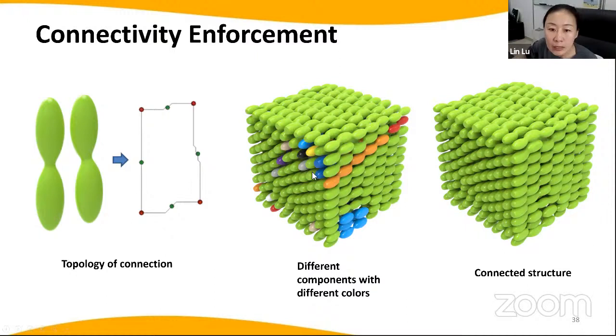For example, here this is the pore structure. The colored pores, rather than the green pores, are disconnected, or they are all different components. So for this one, they indicate that these pores will be closed after we generate the porous structure. So we need a connected pore structure. So we want to guarantee this.